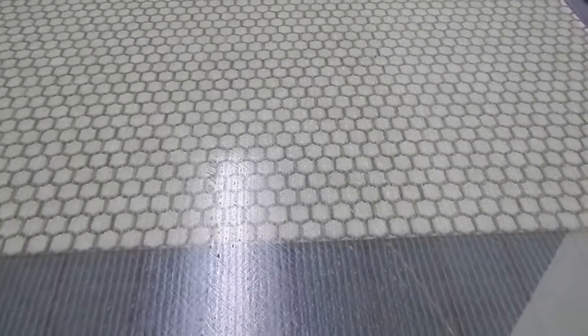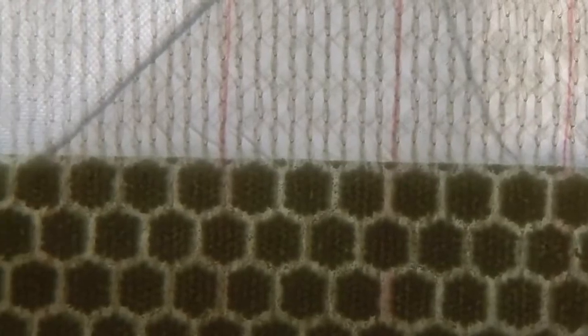You can see some shrinkage in the surface. Like that little bit in the light there. It's where some of the tows were broken up and there's more resin on the surface than there is fiber. This is why you use a print blocker for really nice surfaces because it tends to print through.